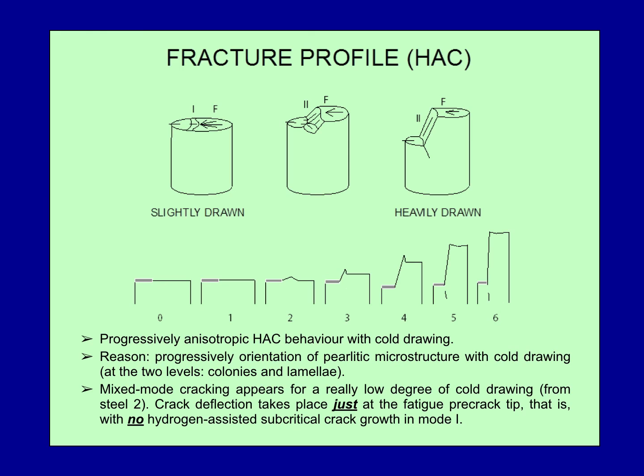With regard to crack paths, hydrogen-assisted cracking paths, we see the picture of slightly versus heavily drawn steels in 3D view, increasingly anisotropic fracture behavior, and the fracture profile showing the crack paths under hydrogen embrittlement condition and the increasing crack path deflection angle with the degree of cold drawing in the presence of hydrogen. We have a progressively anisotropic hydrogen-assisted cracking behavior with cold drawing, the reason being the progressive orientation of pearlitic microstructure with cold drawing at the two levels of colonies and lamella.